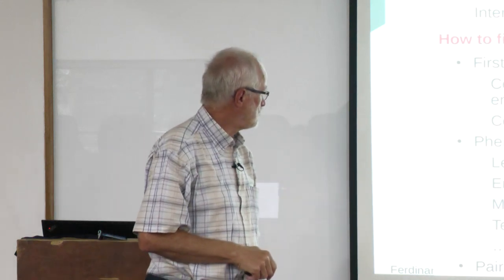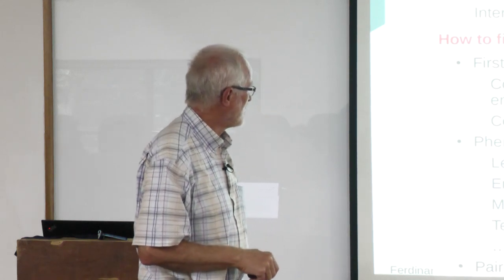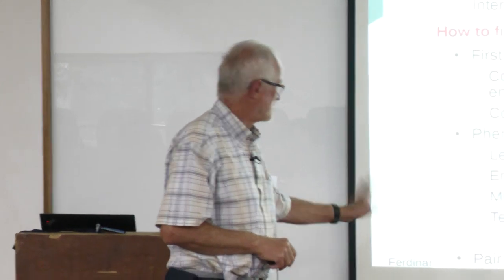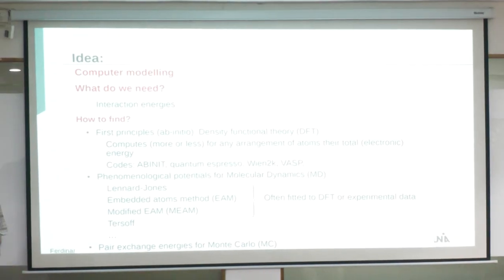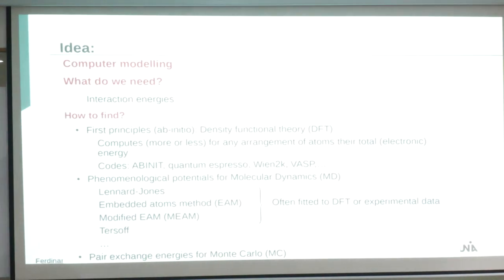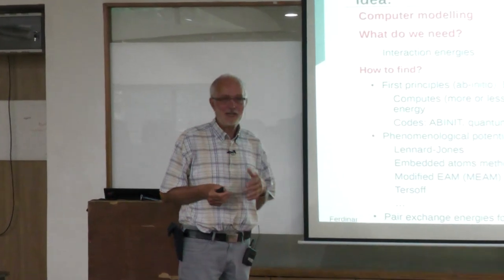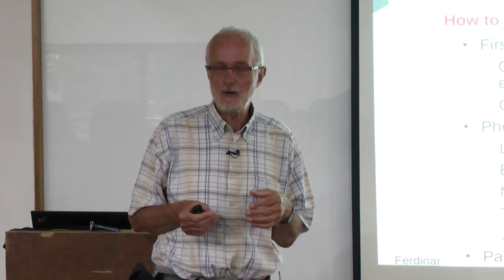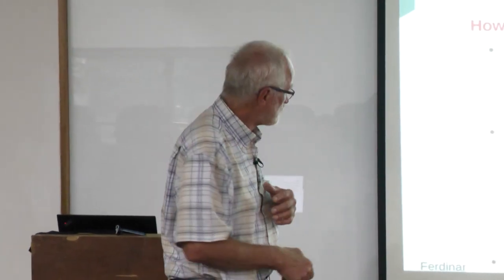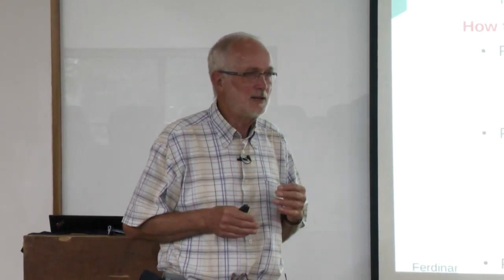in the EAM method. And there are enhanced versions, the so-called modified EAM. I will also explain what it is. And the EAM and MEAM are in particular useful for metals. And since I have a metal or physical metallurgy background, that's what I am interested in. But for other applications, there are other types of interaction potentials. Tersoff, for example, is for semiconductors, I think a good one.